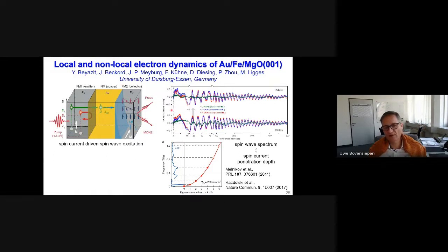And this is data here in the magneto-optical Kerr effect as a function of pump-probe time delay, where we see rather complicated oscillatory responses. We can analyze this by doing a Fourier transform, and this blue line is the Fourier transform. So we can identify 1, 2, 3, 4, 5 modes, and those 5 modes match very well with standing spin wave modes that are indicated here in this iron layer.